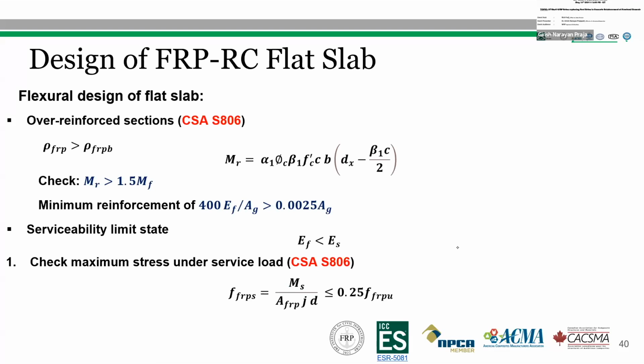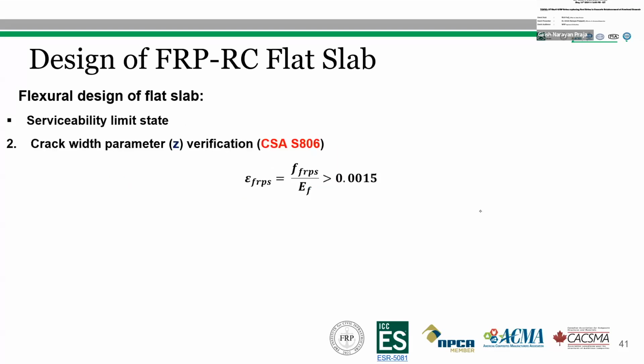The first check is for the maximum stress under service load using the following equation. And the code allowed stress under service should be lower than or equal to 25% of the ultimate stress of the FRP bar. And since we know the maximum stress in the FRP bar under service load and the modulus of elasticity of the FRP bar, we can get the strain under the service condition. And when the maximum strain in the FRP bar under service load exceeds 0.0015, the crack width parameter Z should be verified.